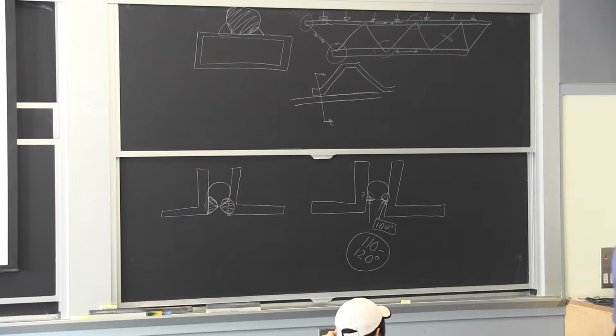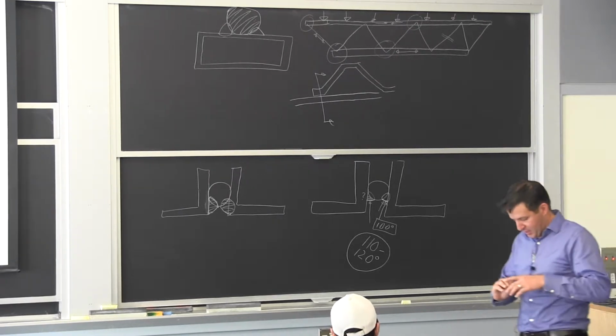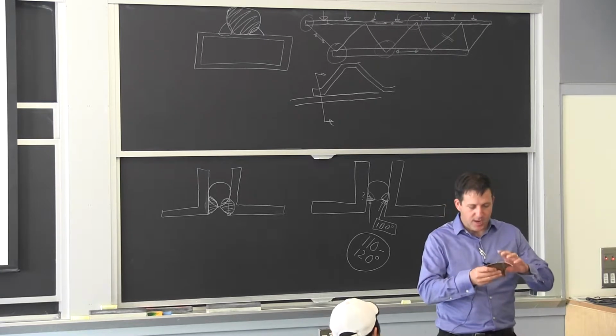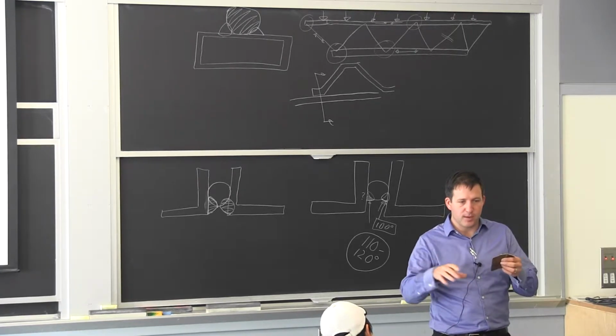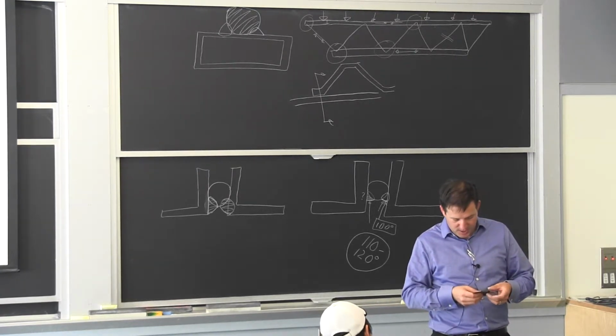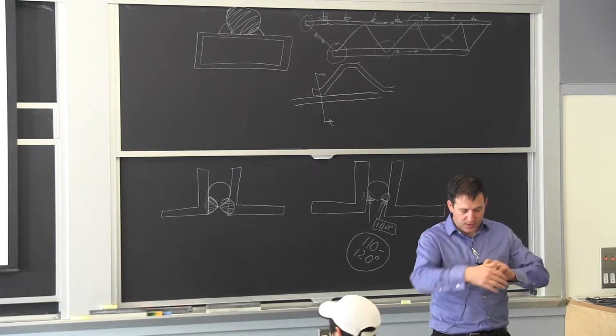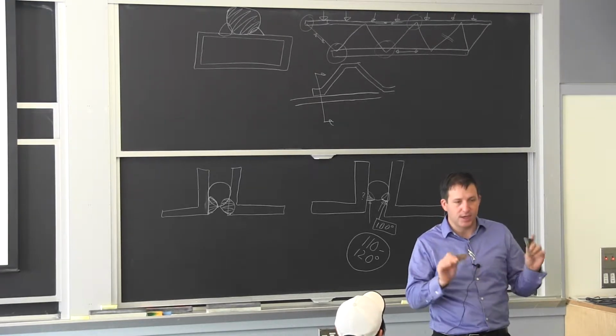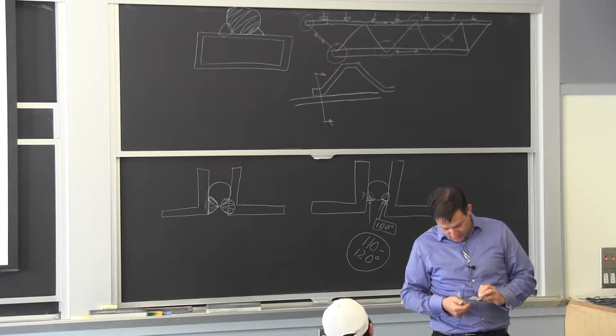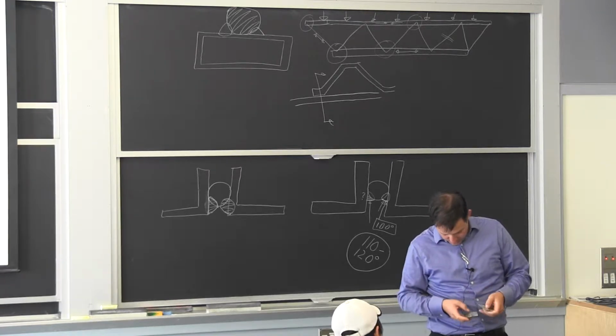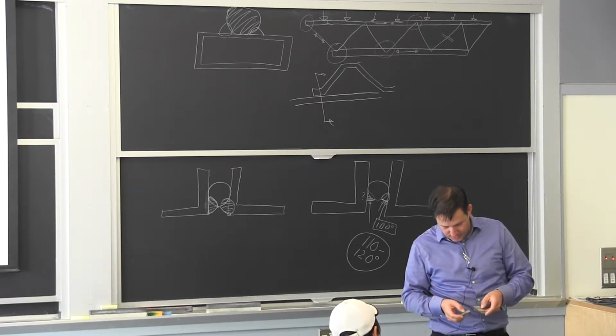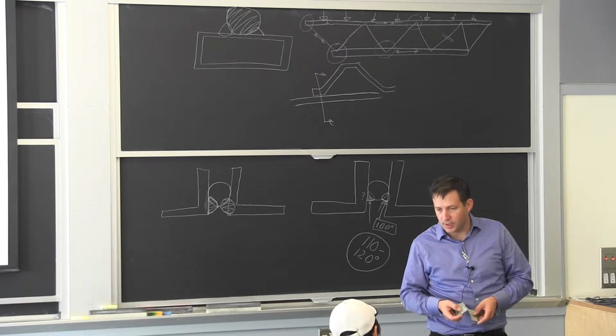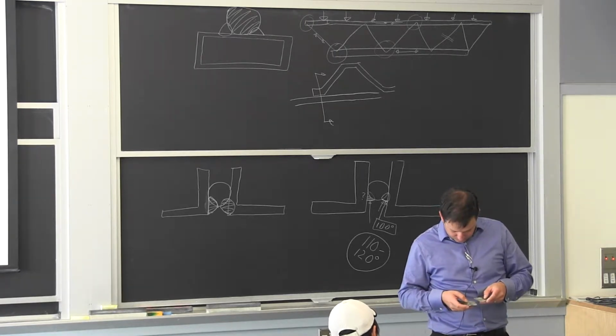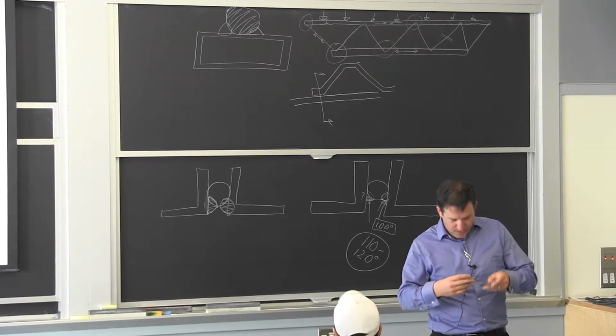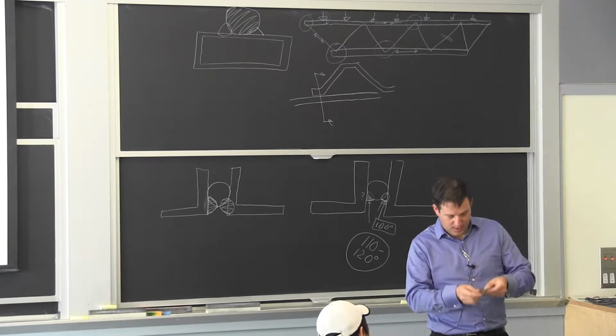I'll pass around the example of brazing. So I was mentioning about the socket joint. This was essentially a pipe elbow going into a straight pipe. And what we did is we cut it in 3 pieces and then we flattened the joint. It just undid. So what you can see is the copper, the original copper, and what you're looking at is the soldering alloy. They go like this,